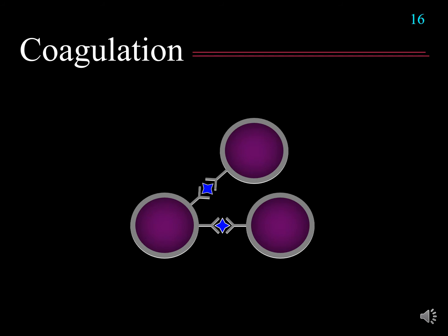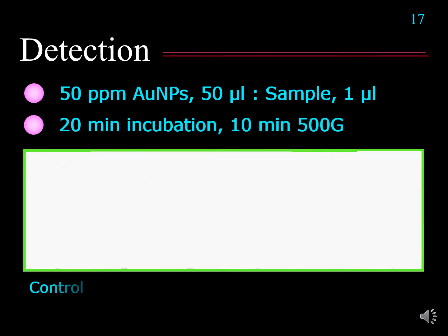They aggregate themselves together. With the increasing size of the nanoparticles, we have scattering. The cluster of gold nanoparticles can scatter the light, and as a result, the color of the colloidal gold solution changes from red to purple or blue. So then we can use this as a sensor.